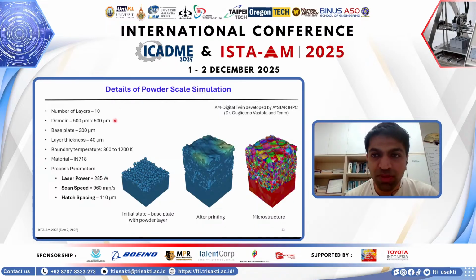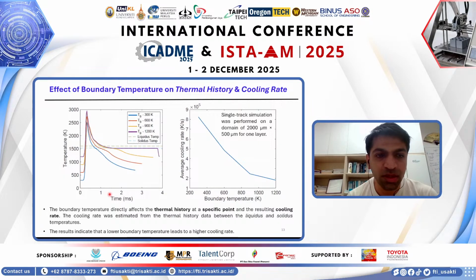And these are the details of the powder bed simulation that we have carried out together with our collaborators at IHPC. These are the typical laser power, scanning speed and hatch spacing. And of course, these are just typical values. We have varied our process parameters in a range of plus or minus 10 to 20% of these values to see how they impact the overall mechanical property results, both in terms of mean and the variance as well. So here's an example.